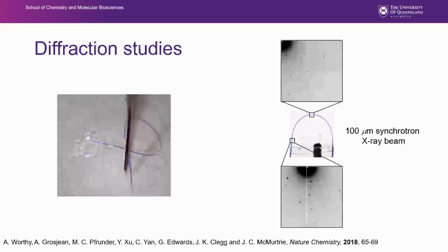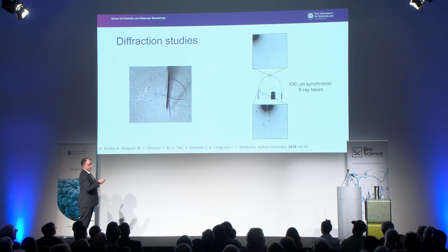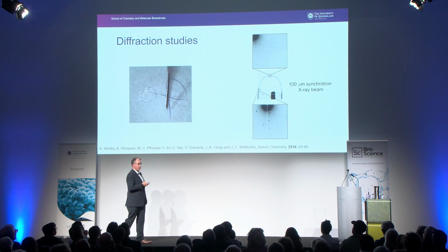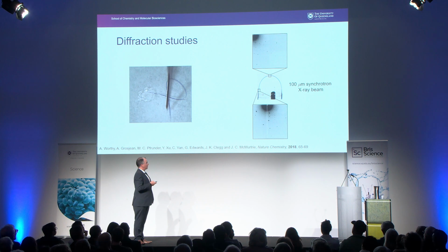So we took some of these crystals down to the Australian synchrotron, where they have some wonderful facilities. It's part of our national landmark research infrastructure. It's a large particle accelerator that makes very, very intense X-ray beams, but it also means that we can change the size of our X-ray beams very easily. So we took some of our very flexible crystals and we fixed them in a loop. And here is our crystal fixed in a loop. And we used a comparatively large synchrotron X-ray beam, 100 microns, okay? So 1/10 of a millimeter in diameter, and we fired some of those X-rays at our crystal.